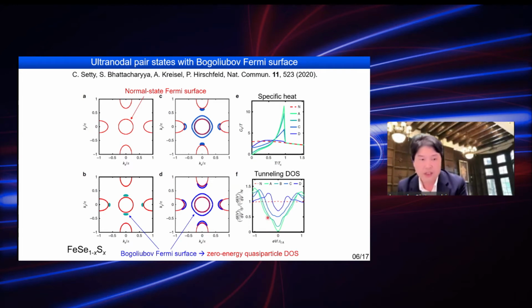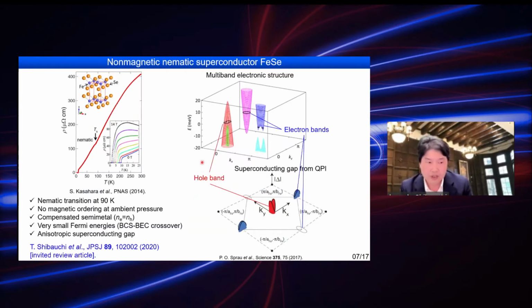So let's look at the experiment. We have been working on this superconducting state of iron selenium. This is a very interesting material, but importantly, it shows the so-called electronic nematic transition at 90 Kelvin, below which you can have a very anisotropic electronic structure. And you can also find superconductivity at 9 Kelvin.